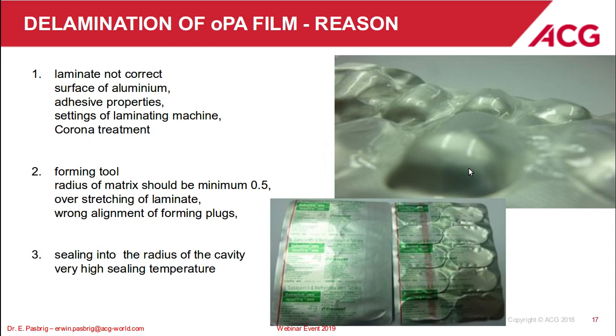There are different reasons for delamination. First, for sure, related to the laminate. The laminates themselves, it's not correct, related to the surface of the aluminium. Could be too much oil, or not oil, it's more or less the additives from the rolling oil on the surface after the annealing process. The properties of the adhesives are not correct. The bonding to the aluminium and to the OPA, it's not good enough, it's too low. That's why it starts to delaminate relatively early.